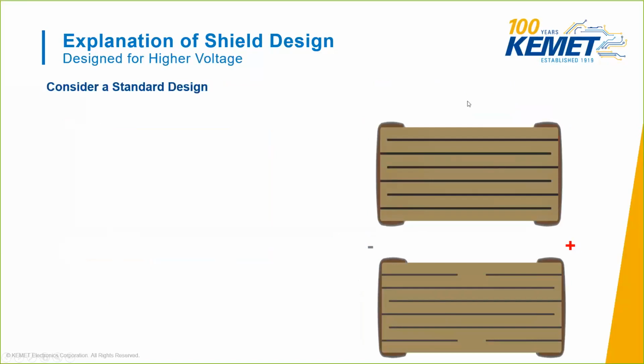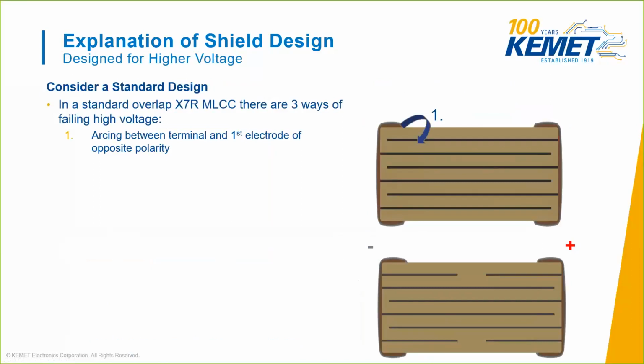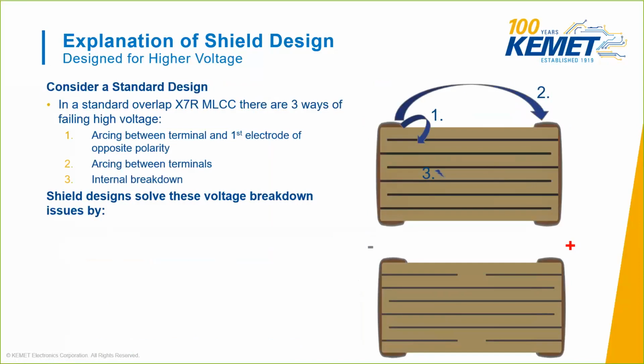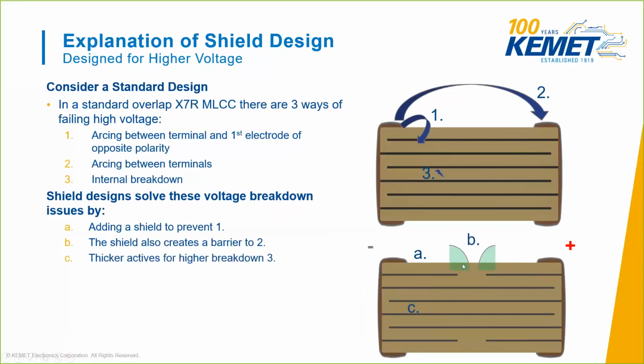Alright, so if we consider a standard design, in a standard overlap X7R MLCC, there are three ways that you can fail high voltage. Arcing between the terminal and first electrode of opposite polarities, you can see here. Arcing between terminals, as you can see over here. And then internal breakdown. If you go too high in voltage and you don't arc, eventually you will break down the dielectric. Now, the ArcShield can help resolve all three of these. One, by adding the shield to prevent that termination to first counter electrode, which also prevents that ionization of air and creating that barrier between termination to termination, and also allows you to put more layers with a higher thickness to increase that dielectric breakdown.